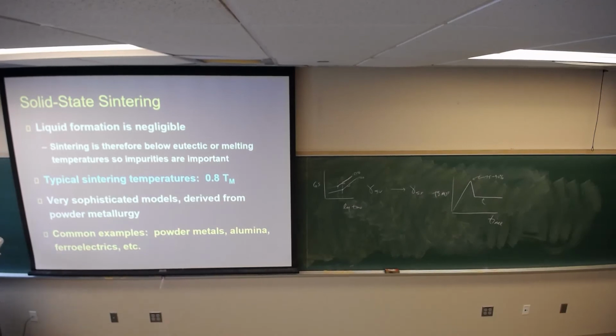And that rule of thumb was developed somewhere in the 50s. I don't believe that rule of thumb is still valid because improved processing means we eliminate the large defects in the pores and we can densify at a lower temperature. And we see that over and over. Plus, as we drive down particle size and drive up surface area, the densification improves at lower temperatures.